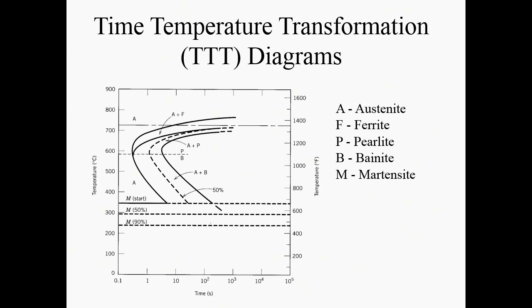So, austenite and pearlite, ferrite and pearlite here, the normal structures. If we cool to 400 degrees C and held, we get another phase which is called bainite. And bainite is just a different mixture of iron carbide and ferrite. It has little particles of iron carbide rather than the lamellar sheets of iron carbide. Because it's formed at a lower temperature, carbon can't move so far, can't diffuse very far, because the temperature is lower. So we end up with a different microstructure.